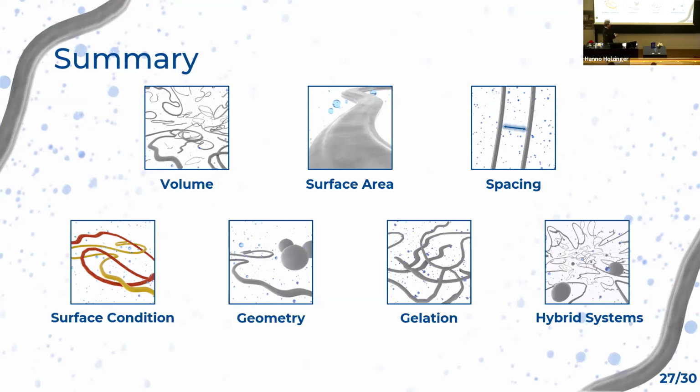of water. In gel systems, salt screening restricts not only the fiber motion, but also leads to a more confined network. And finally, in hybrid systems, it's not just the global charge balance, but actually the nanoparticle charge itself that controls whether these particles either merely coexist or actually lead to a restructuring of the network, as we now interpret it with these differently charged CNF dispersions, through the electrostatic interactions.